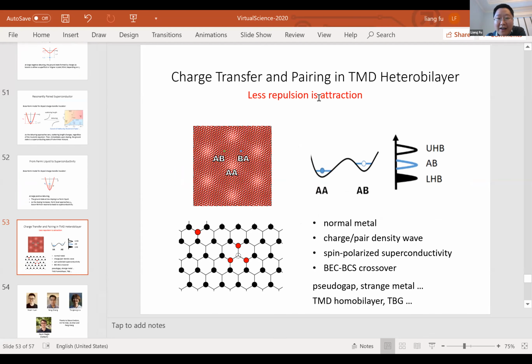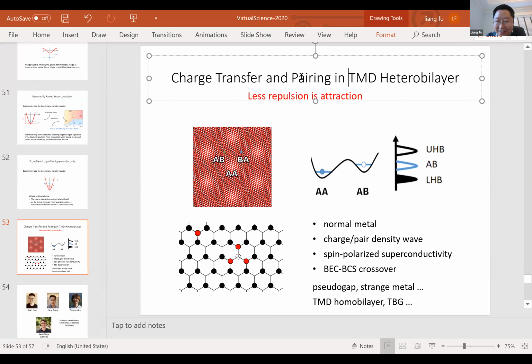Hopefully I described to you some of the interesting physics that still needs to be seen in transition metal dichalcogenide heterobilayers. Starting from this moiré superlattice, we see that there are two types of potential minima in the AA region and AB region. That's why the low energy physics is that of a diatomic crystal with a cation and anion. And because the energy difference between the two atoms is small, the system at half filling is a charge transfer insulator, and the doped charges go into the cation sites.